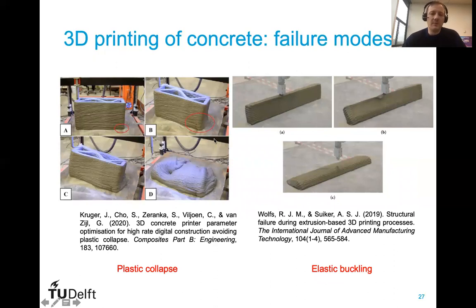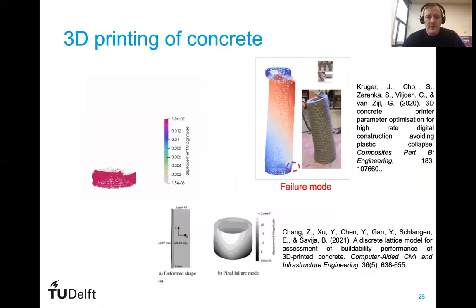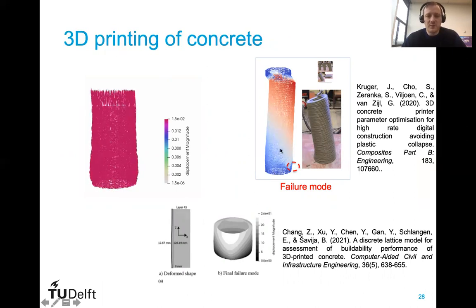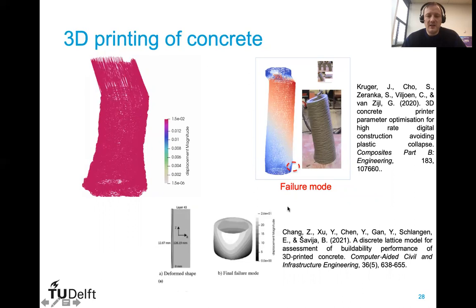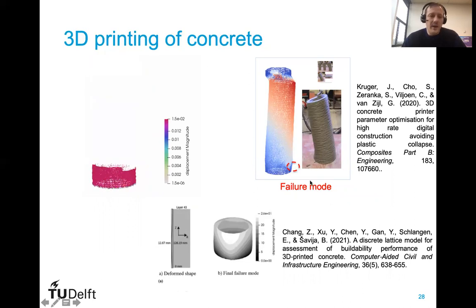So actually, we should be able to simulate both of these failure mechanisms if we are to predict the buildability of cementitious materials and if we are going to control the printing process. So a PhD student of ours has developed a numerical model in the Lattice modeling framework that is able to simulate the failure mode of plastic collapse. So we can predict at which point the structure will fail during printing based on the input parameters that are experimentally measured. The model has been validated against experimental data from the literature. So based on the geometry and on the material properties, we are able to predict at which point the print will fail during 3D printing.